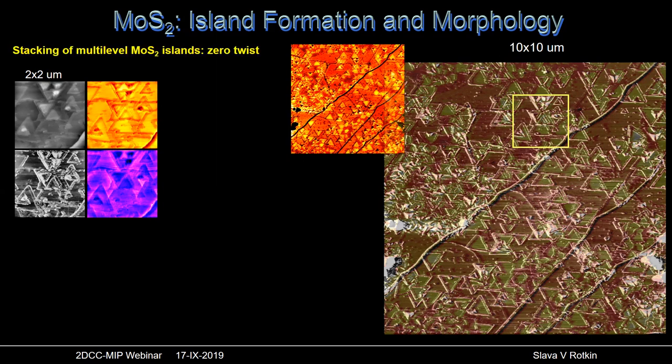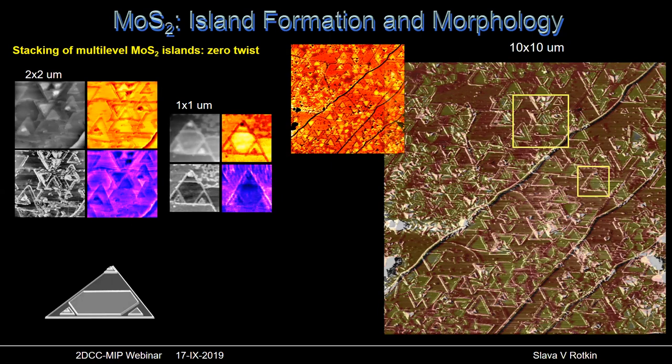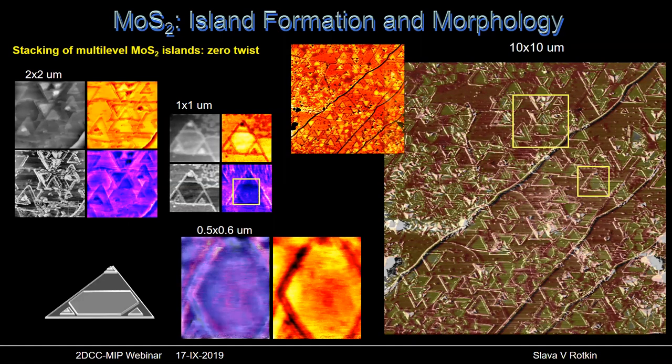So we understand that the stacking of the multilayer MoS2 happens at probably zero twist angle, but it still does influence optical properties of these islands. So we also zoomed in on the area which appeared to be interesting in the low resolution. Here we have a single triangular island, and on top of this triangular island, there is one more hexagonal island, and there are a few more small triangular islands grown as higher level pyramids on top of the major level. Interesting enough is that if you go with an even higher resolution, the central area